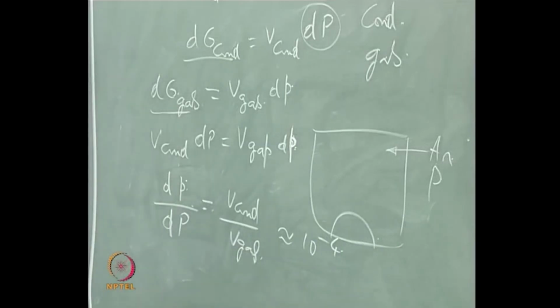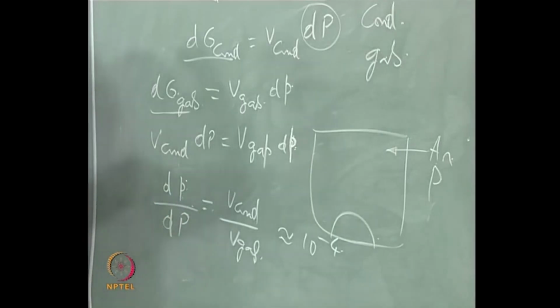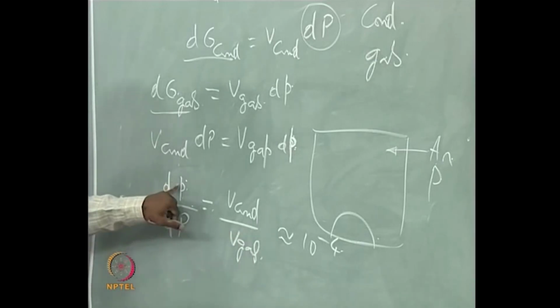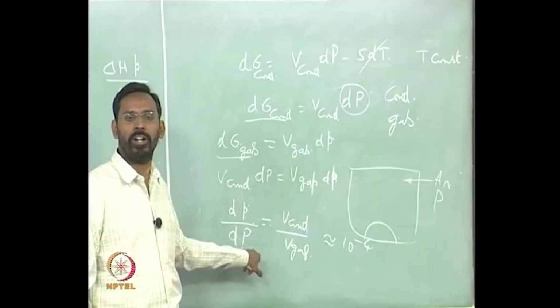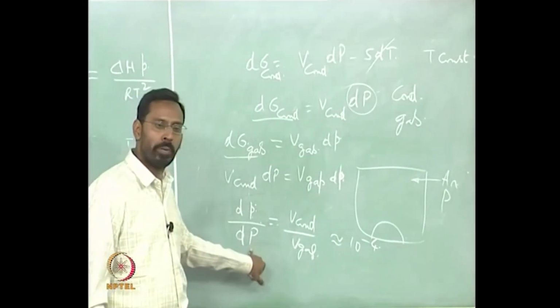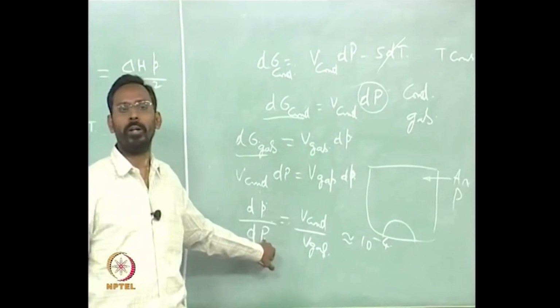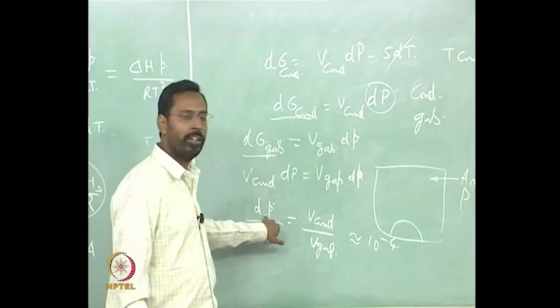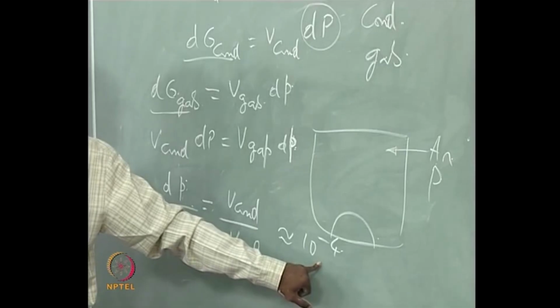So if I have a certain gas inside the chamber, and the gas pressure inside the chamber, how does it affect the partial pressure of the gas that is generated because of sublimation? You can see that the partial pressure of the sublimated gas does not get changed by the external pressure to a large extent unless this pressure is very, very large. If I take this as 1 atmospheric pressure, at 1 atmospheric pressure this P changes only by 10 to the power minus 4, not much.